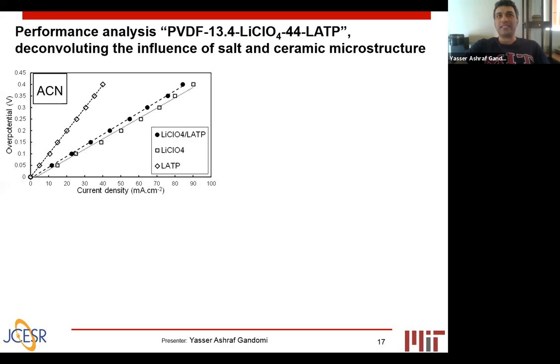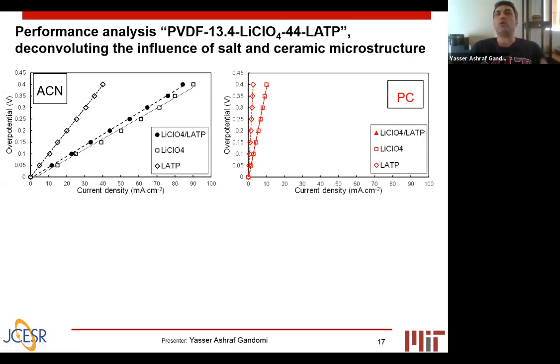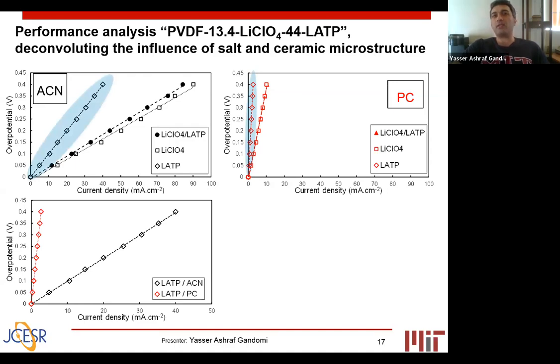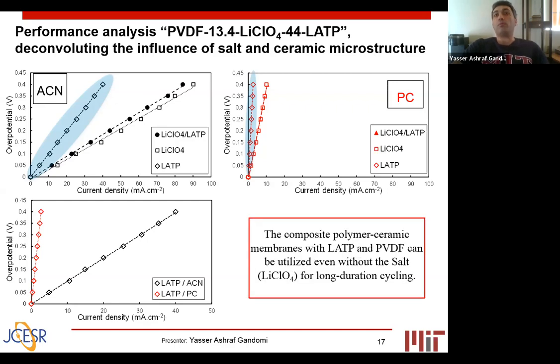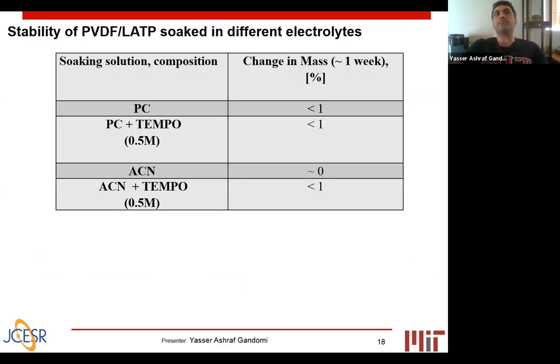So it was necessary for us to reassess our synthesis and prepare membranes without the salt. Here I'm showing you 3 different configurations of the membranes we synthesized: LATP and PVDF only, and then 2 different configurations with ceramic and salt and with salt only. And we ran these experiments with PC and acetonitrile. It's very clear that when we do not use salt within the structure, the performance is compromised. However, if we look at the performance with LATP and PVDF only, we can achieve up to 40 milliamp per centimeter square with acetonitrile and about 5 milliamp per centimeter square with the propylene carbonate. Therefore, they are promising membranes to be used for long duration cycling if our purpose is not to achieve high performance. And the last step was to make sure that the mechanical stability is maintained.